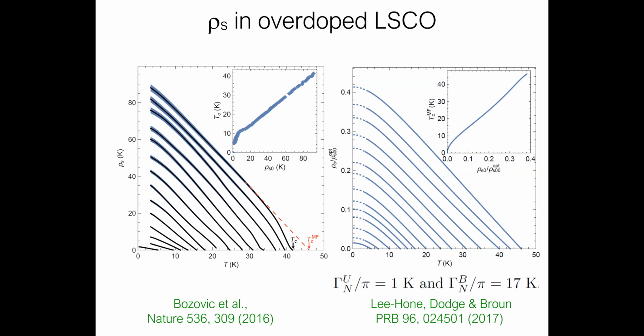I see. Thank you. The other question I had, you mentioned the correlation being on the length scale of the unit cell to produce some of the effects of the disorder level that you see. Could you comment a bit more on how you control this correlation length? In the simulation, it's controlled by simply having a fluctuation of the BCS pairing potential with a Yukawa form and putting in a range. And so we studied ranges from unit cell size up to many times the coherence length. And basically, unit cell size up to nearly the coherence length gives you very similar results. Once you get longer than that, obviously the response of the system is being averaged over the coherence length rather than the pairing fluctuation. I see. All right. Thank you.